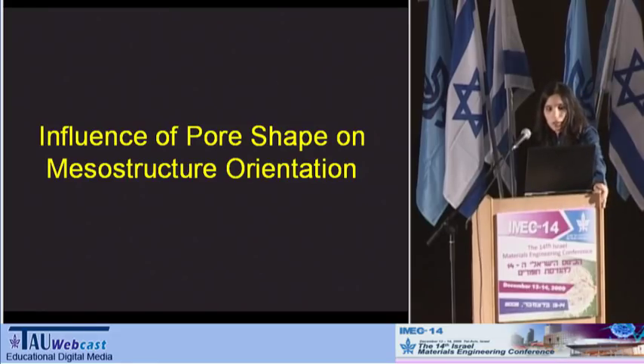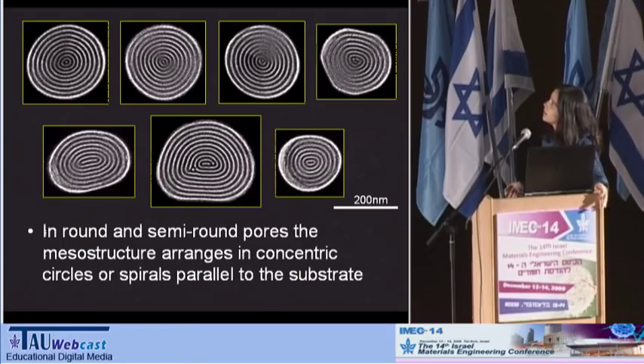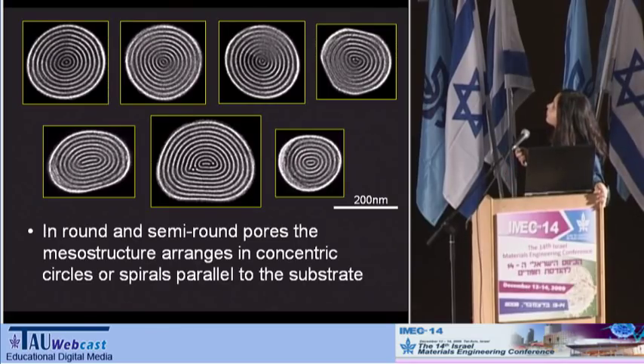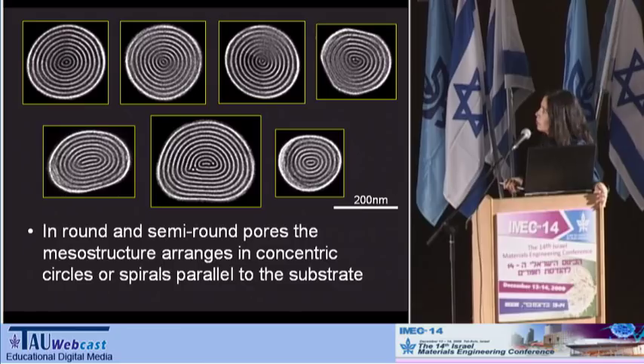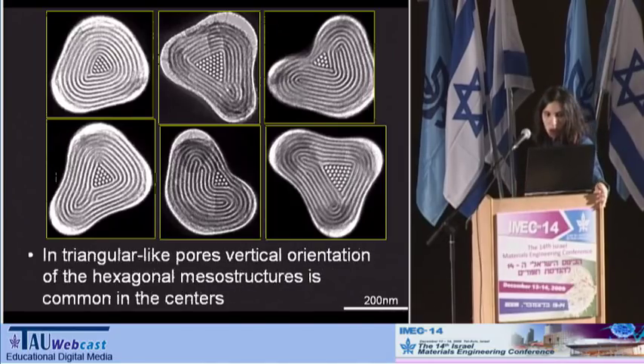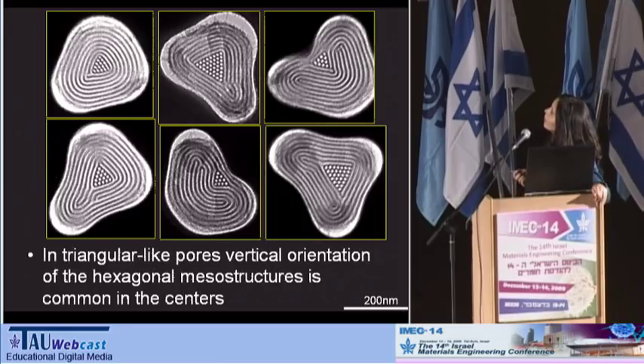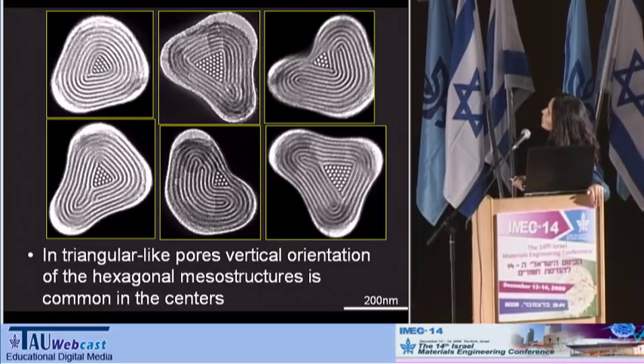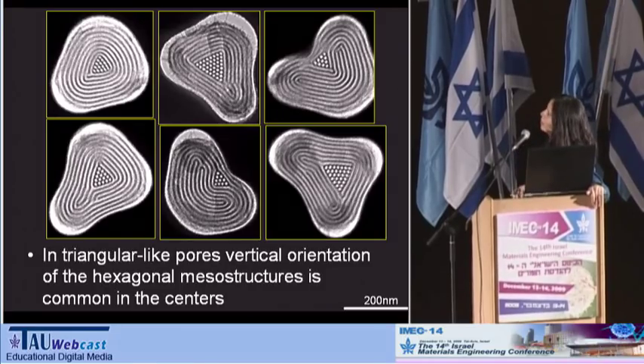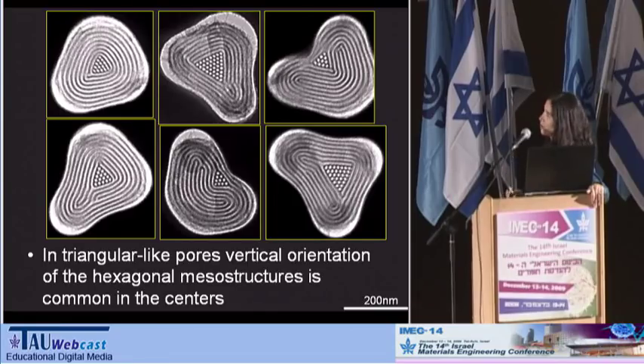During our experiments, I noticed there is a strong influence of the pore shape upon the obtained mesostructures. I could see that in round or semi-round pores, the mesostructures form spiral-like or stack-donut-like circles inside the pores, oriented horizontally to the substrate. But in triangular-like pores, I see very often the vertical alignment that I would like to achieve. Our hypothesis is that it is not energetically favorable for the cylinders to undergo a curvature stiffer than a certain angle, and under these conditions they will choose, for energetic reasons, to align with the long axis of the pore.